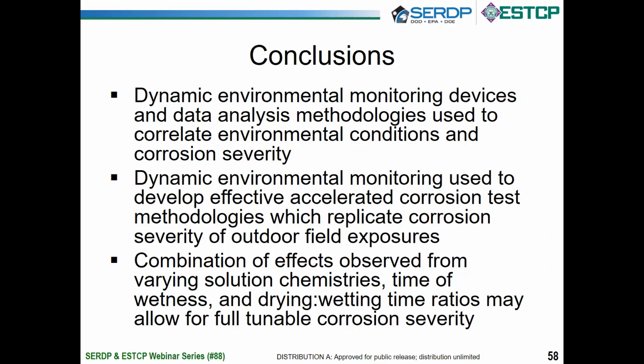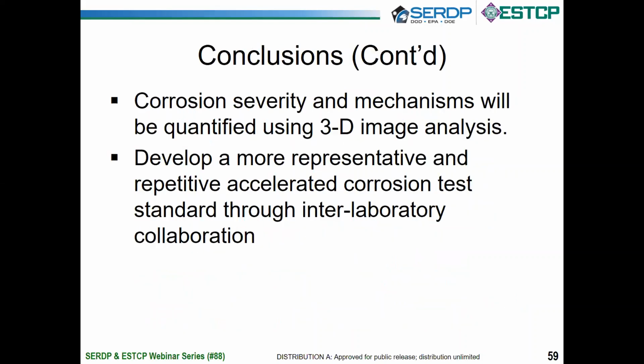Also, we plan to observe more the combination of effects observed from varying solution chemistries, time of wetness, and drying to wetting time ratios, so that we can fully tune corrosion severity as well as better control the method of attack during those tests, so that they're more representative of what we would see in the operational environment. Slide 59, please.